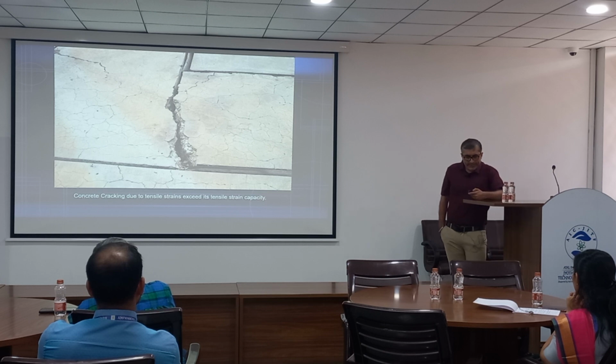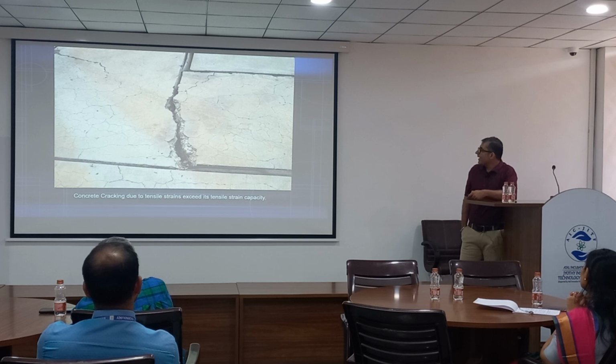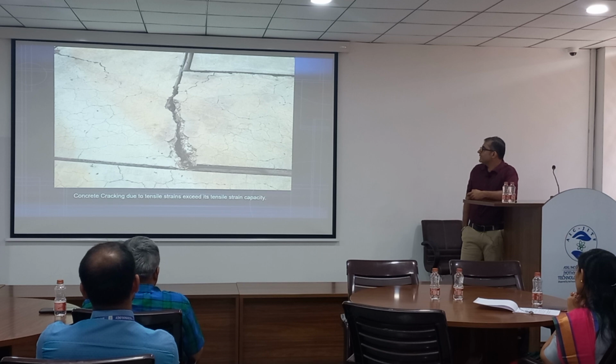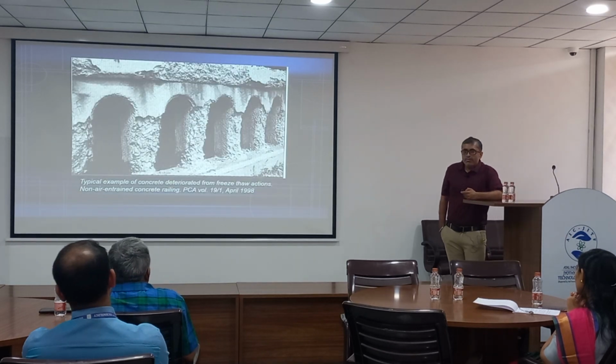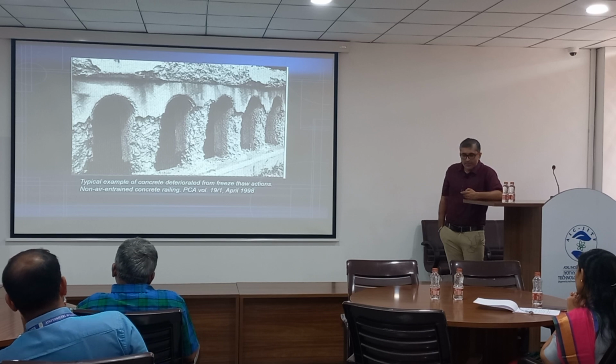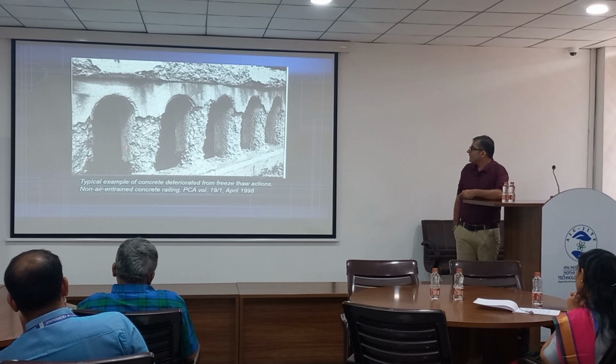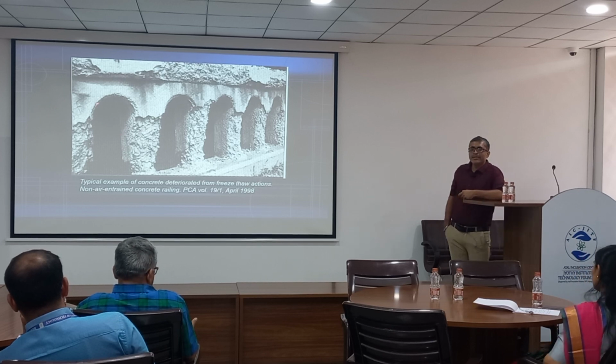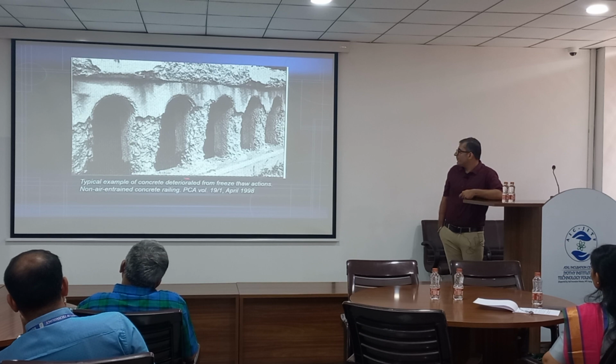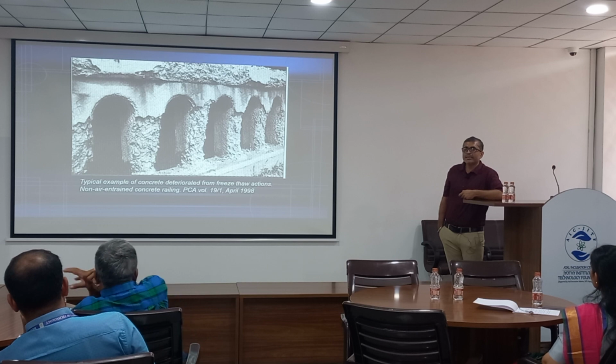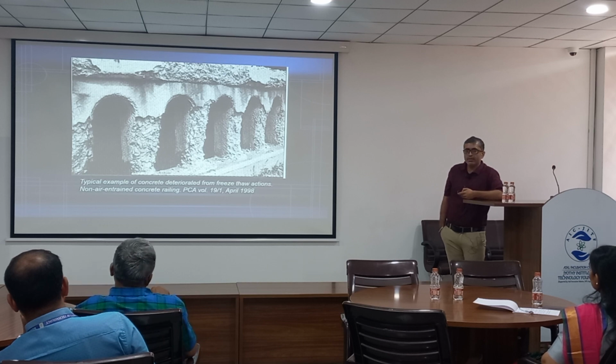So when the tensile strains exceed its capacity, this can happen. Here is an example of a crack which has occurred in the slab. This is one where the concrete has undergone deterioration. Look at the way the portion has deteriorated. This is because of the freeze-thaw action. This is very predominant in structures built in cold environments or cold regions.